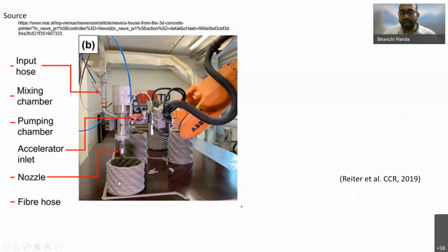But the point is, if you want to do the same thing for the previous mix design, we have to do some modification at the nozzle, because to control the material buildability, we have to find some solution so that once you deposit the material, it is quickly going to get hardened. So there are different solutions you can adopt at the nozzle so that the material can be hardened.